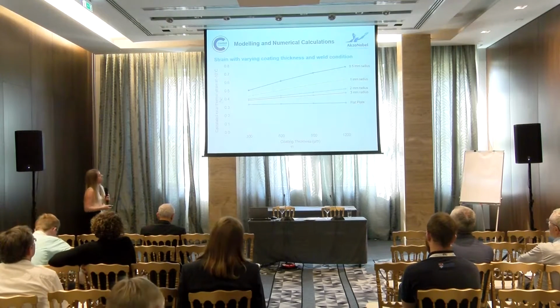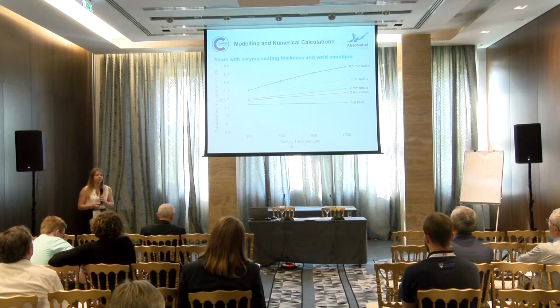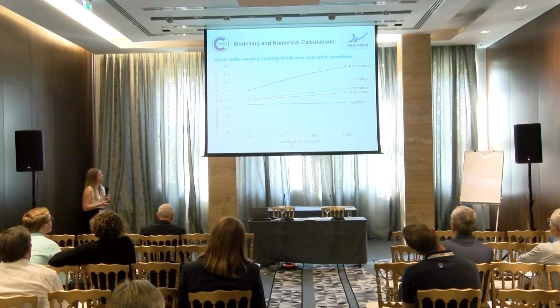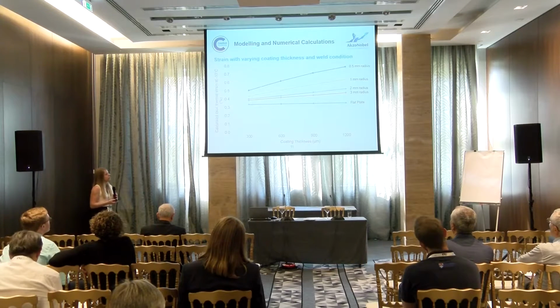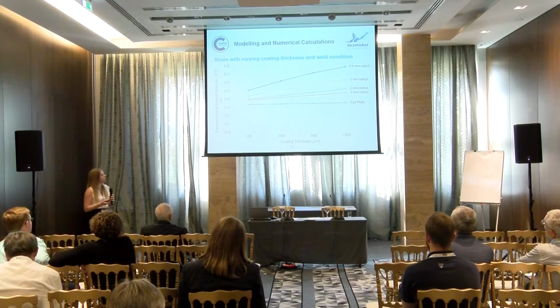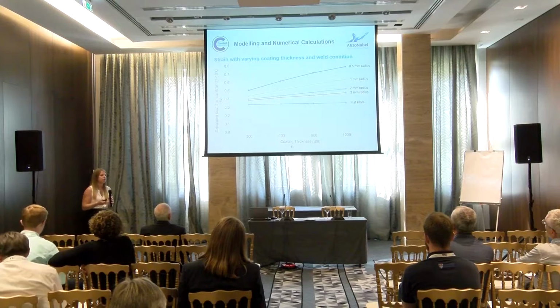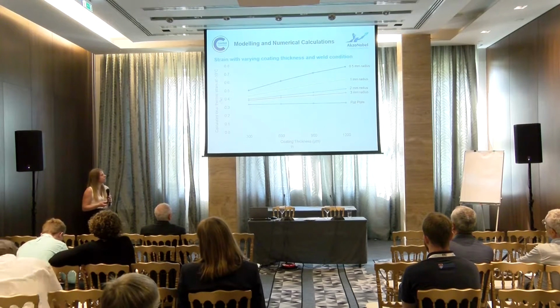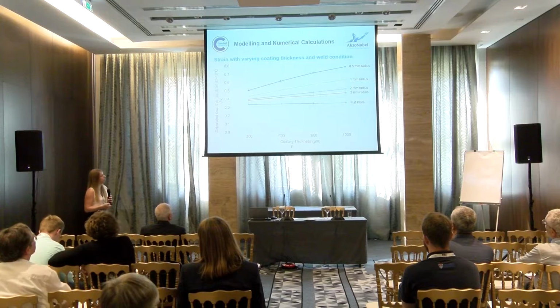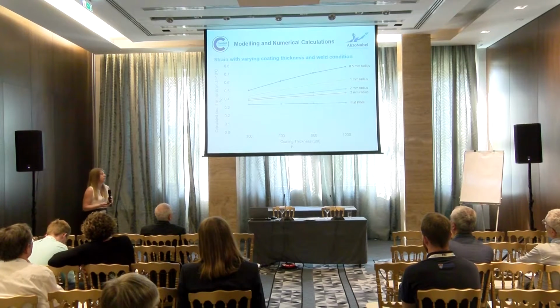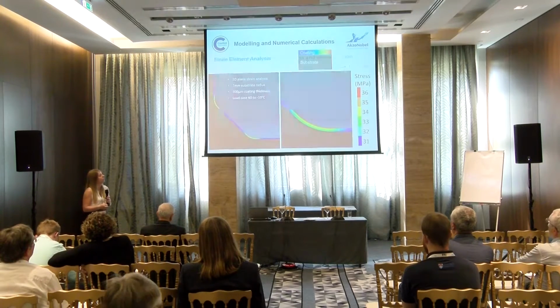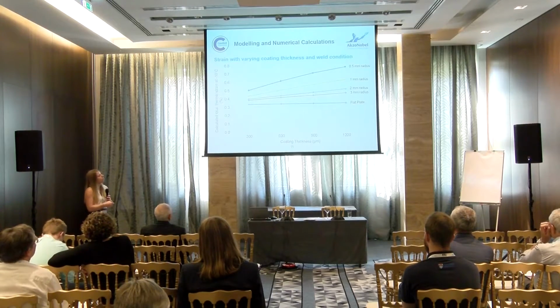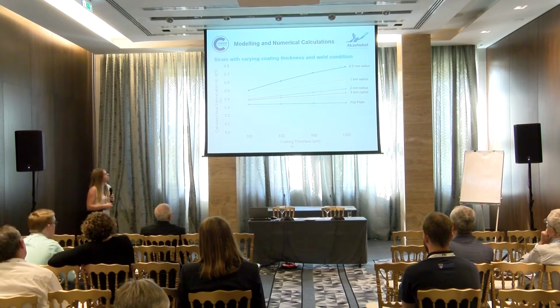And a series of models were carried out in order to investigate the effect of coating thickness and weld fillet radius. So sectioning of the actual T samples, and an analysis of those, showed that in each sample there could be a thickness between 300 microns and 1,000 microns present. It also showed that on the non-milled weld there could be weld fillet radii from 0.5 to 3 millimeters.